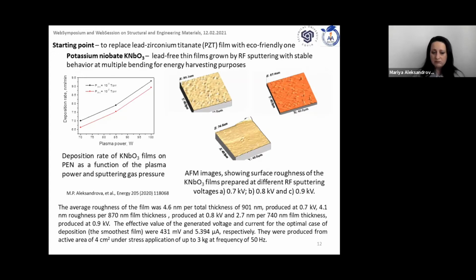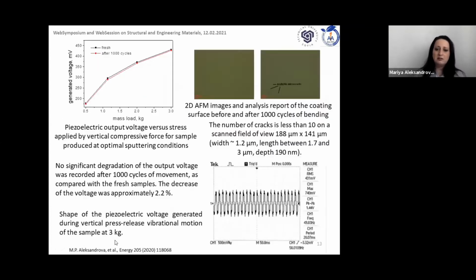It is helpful to attain 400 millivolts and 5 microamperes electrical parameters, which is really good considering the whole thickness of the element, which is not greater than 1 micrometer, and an area of 4 square centimeters. So after 1,000 cycles of repeating bending, we found that the voltage decreased by 2.2%, which is really stable.